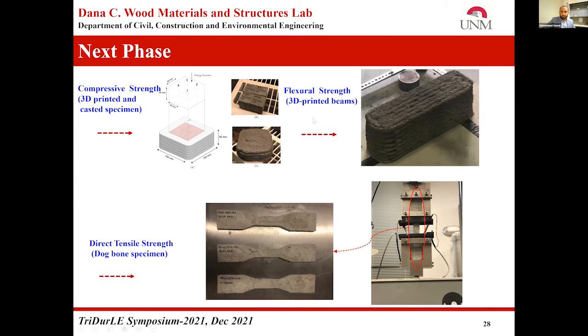To assess the flexural strength, 3D printed beams were printed by using these mixes. And for assessment of direct tensile strength, dog bone specimens were used.